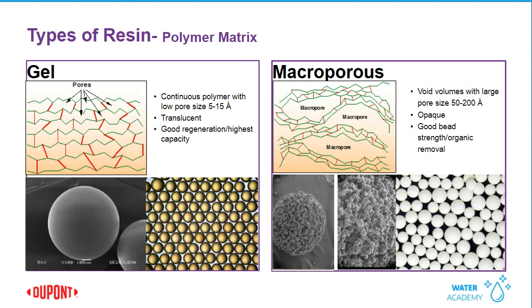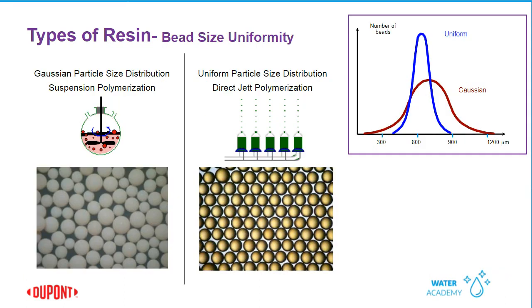We make our copolymers by two different processes. One is a suspension polymerization, and the other is a direct jet polymerization. These processes result in product with different bead size uniformity. On the left-hand side, I'm showing a suspension polymerization. And in the micrograph, you can see that the beads are of various sizes. We refer to this as a Gaussian particle size distribution. On the right is a direct jet polymerization. All the bead sizes are very uniform, and we refer to this as a uniform particle size distribution, or UPS for short. On the top right of your screen, you can see an overlay of the particle size distribution for each type, for the Gaussian and the uniform. We're going to talk more about particle size later on in the webinar.